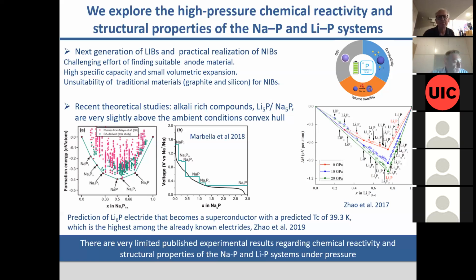So I think, when we did the cubic nitrogen or our first runs on silicon nitride, to look more closely, you take what you think you made and you measure the Raman shift, or you measure the compressibility by X-rays to see if you have a drastic change in these properties. So I think this is a little bit lacking in all this. You know, quick papers, new compounds is great. Most of it is probably okay, but the testing should be done a little bit more carefully in my eyes.